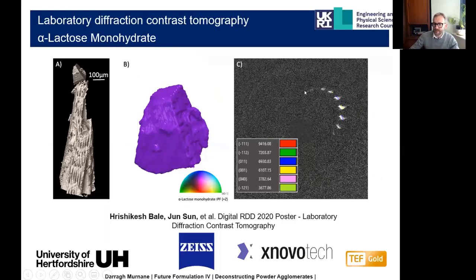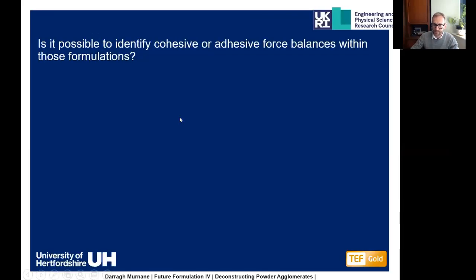We can see here the simulated diffraction spots for that particular crystal, and from that we're able to work out the orientation. So you can see we're somewhere along this step of being able to pick out the orientation of a particle based on its crystallographic diffraction results. So the next stage for us is to move this on and start to look at multiple particles at the same time, and to try and see whether we can index the crystalline faces to which the drug adheres.